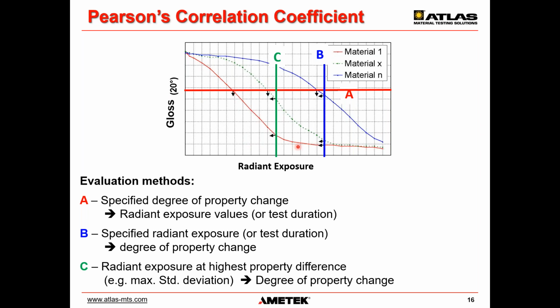And actually, the best way to approach correlation, to select data for correlation, is you do a continuous exposure, have a continuous recording of the gloss over the full exposure time, and then you pick the time where you have the biggest differentiation between the different data. You can do a simple standard deviation, and where you have the maximum standard deviation between the different data points, that's the best time to actually do a correlation study. This shows the biggest difference between the different test materials. It's the highest effort, method C, but it's probably the best way to approach correlation.